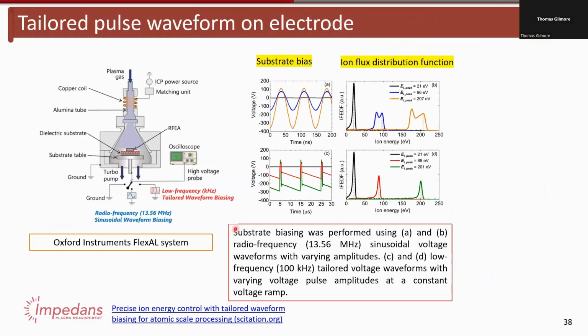This is in an Oxford Instruments Flexal tool. If you apply RF to a bias, this is an example here. With one power, you get this blue wave. As you increase the power, you get higher voltage, so you get this yellow-orange wave being applied. Then if you look at the resulting distribution function, with the smaller power you get this, and with the higher power you get this, like I've shown you previously.